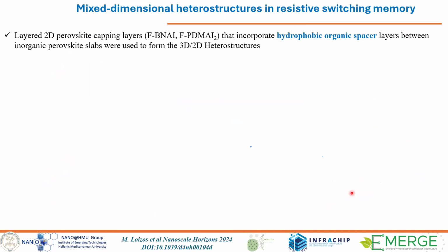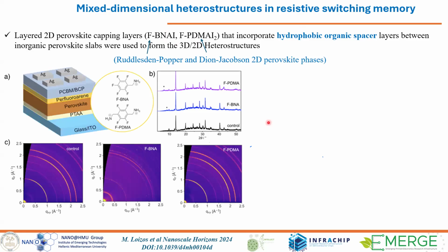This is another work with our colleague Giovanna Milic, she is in Finland. Okay, we have a 3D perovskite. So we thought, okay, what about putting a capping layer on top? Specifically a 2D layered material, perovskite capping layer. So Giovanna provided to us two different types, Ruddlesden-Popper and Dion-Jacobson 2D perovskites. Okay, we name them here BNA and PDMA. And then we wanted to see if this passivation layer is going to improve mainly the stability, but also affect the performance of the memristors.